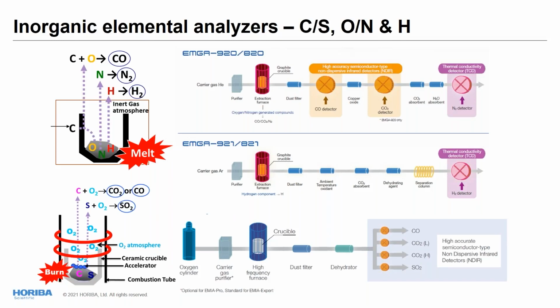You can see here the generation of gases for oxygen, nitrogen, and hydrogen happens the same way in an identical furnace, but in many cases, the hydrogen system is a dedicated one to provide better performance for hydrogen detection and better detection limits than with combined systems that can do all three gases together. In such a setup, the hydrogen will be detected using a TCD detector that is the most sensitive detector for this element.